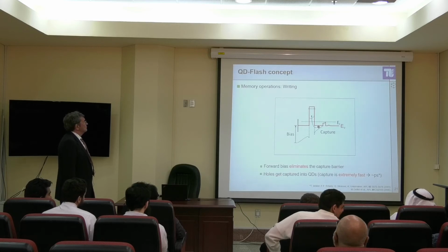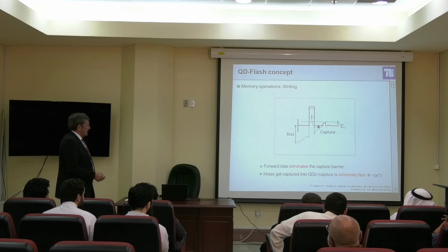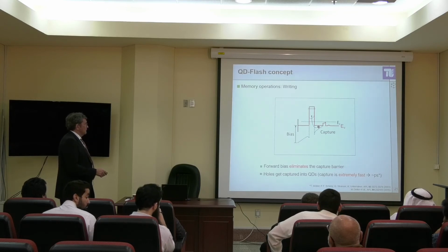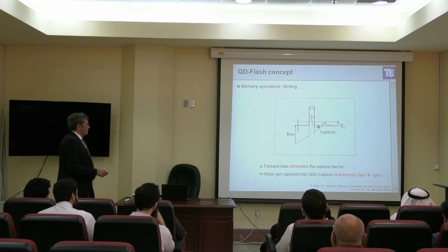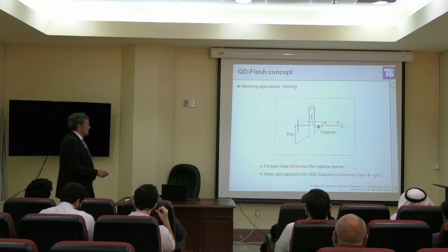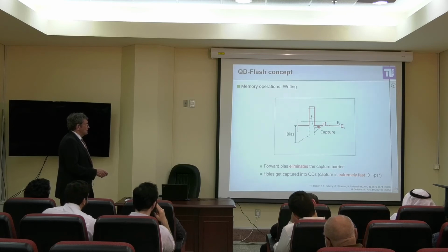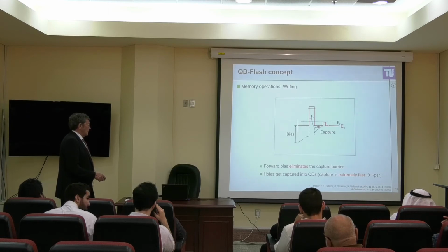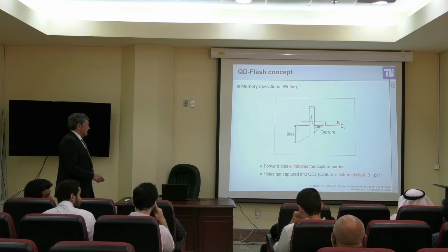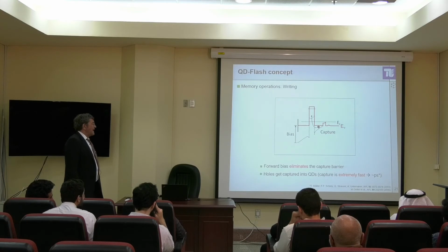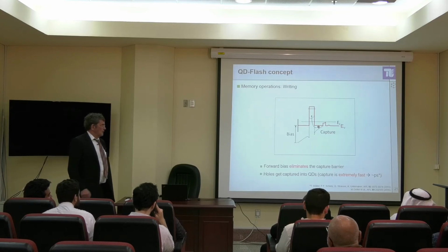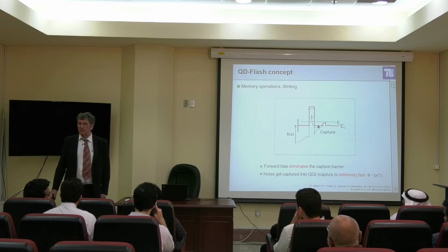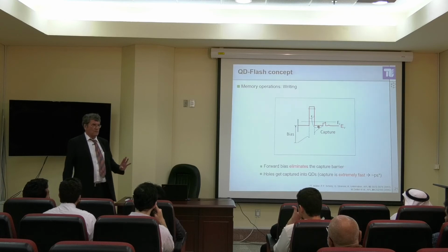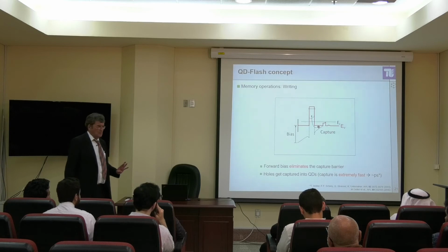Memory operations, now writing. Now you change the bias. Now the dashed line is here. You apply a positive voltage here and pull it down, and then you can capture carriers which are here in this 2D layer. Forward bias eliminates the capture barriers and holes get captured in quantum dots. That is extremely fast. I say here it's picoseconds, it can actually be faster than picoseconds, down to 500 femtoseconds. Very, very fast.